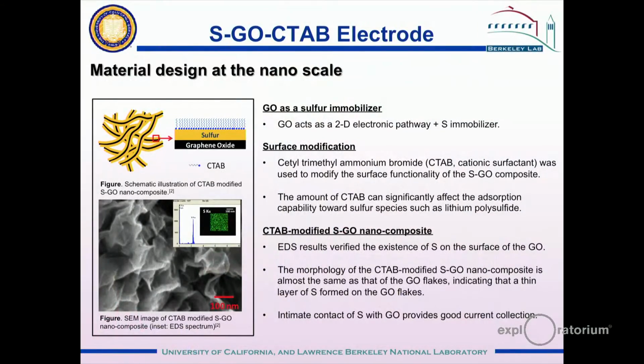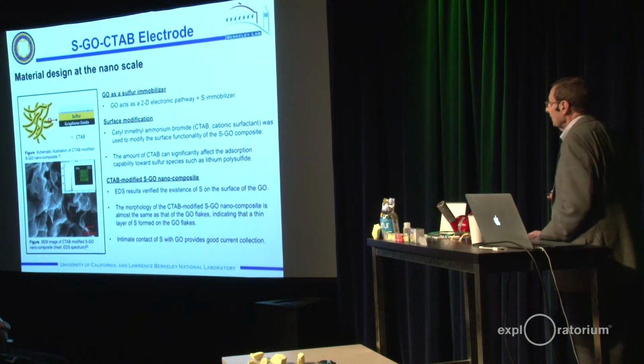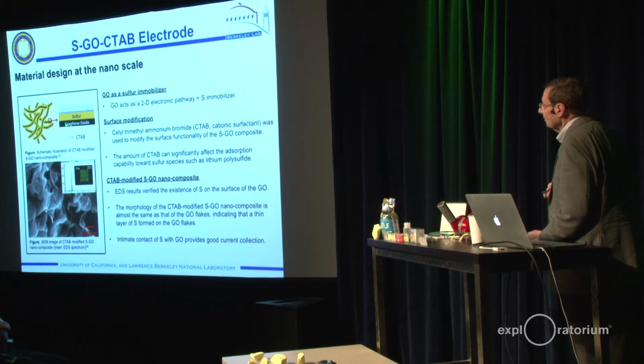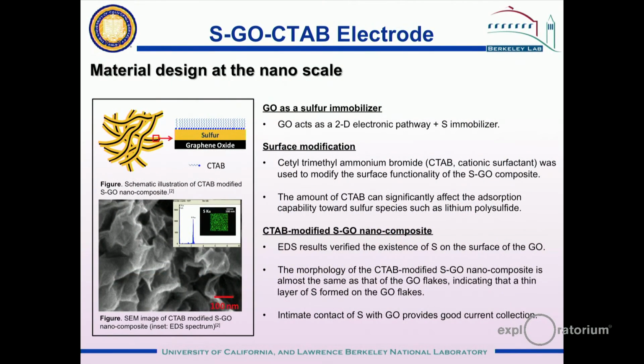But in order to get that kind of performance, we must very carefully construct the sulfur electrode so that we can utilize all of the sulfur that's in that electrode and get the maximum capacity. So we have found that if we combine on a nanoscale the sulfur with a conductive material, graphene oxide in this case, to form a very thin and uniform coating over the surface of graphene oxide flakes, and then we further protect the sulfur using cetyl trimethylammonium bromide. So these are long carbon chains that adsorb on the surface of the sulfur and protect it from dissolution.